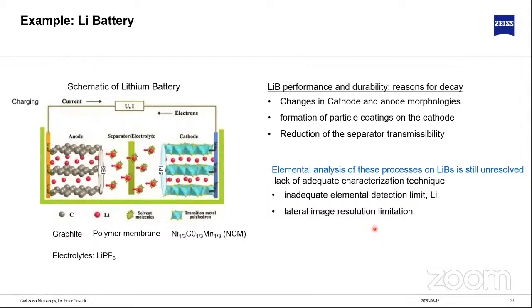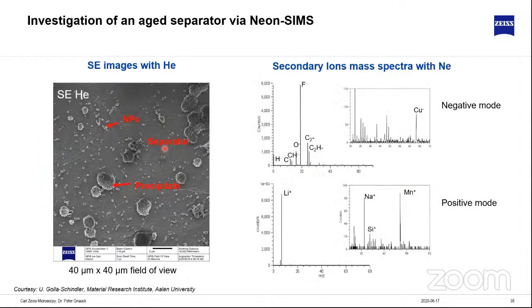And I'd like to start with an example looking at a lithium-ion battery. My example is actually the separator that we want to look at. The separator sits in between the cathode and the anode, and it's suited to let the lithium ions pass through and prevents these two, the cathode and anode, from actually connecting to each other to avoid any shorts. If we look at an aged separator that has been used before, and we just take an image, we see this separator foil here in the background, and then we see a lot of dirt on that. We see some nanoparticles, we see bigger precipitates, and it would be interesting to see what all this stuff is. So we can do a mass spectrum of the whole thing, and we see a lot of different elements here.